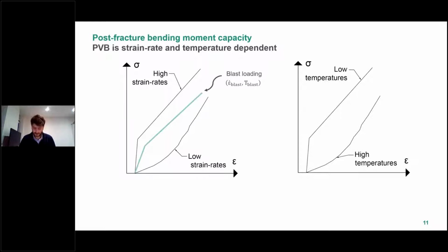PVB is also sensitive to temperature, and using previous experimental work, I demonstrated that there's a time-temperature dependency similar to many other polymers. Therefore, the PVB response at high strain rates can be simulated with low temperatures by deriving a time-temperature mapping equation. This uncouples inertia effects and allows the investigation of the pseudostatic bending moment capacity.